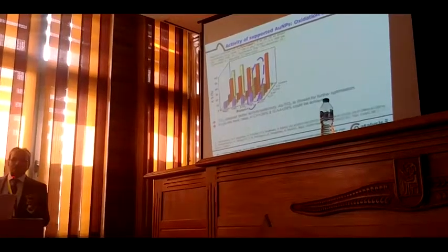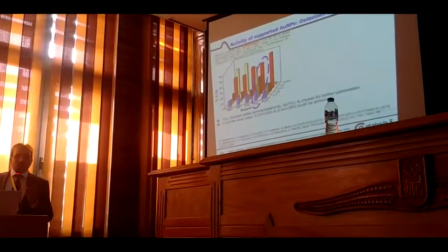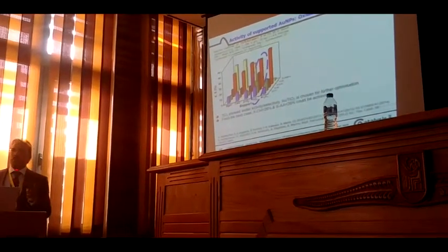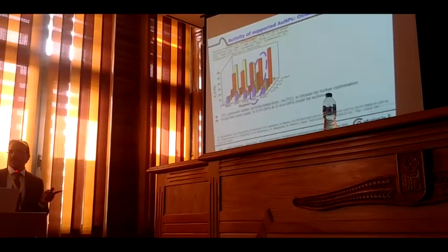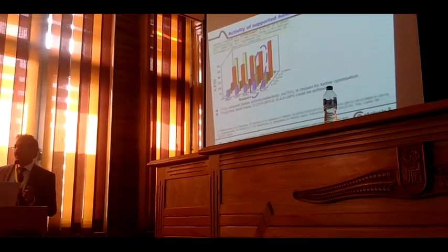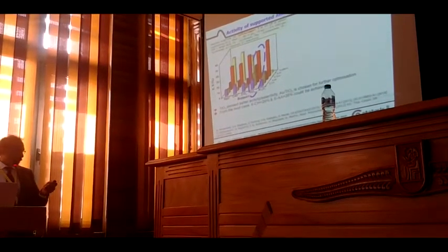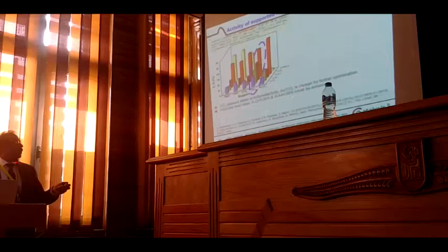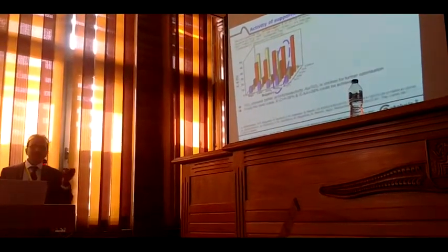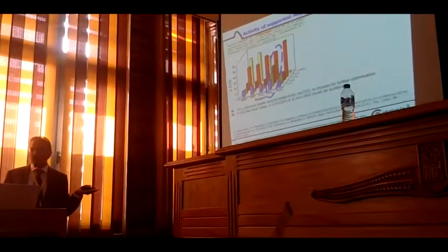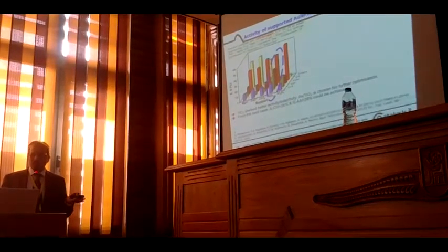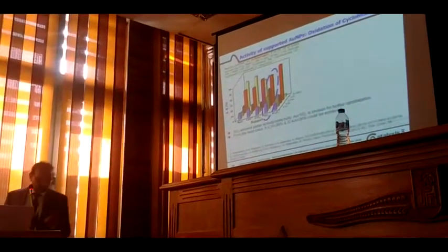But still, until now, to our knowledge, there is not even a single publication where adipic acid is produced in one step directly from cyclohexane. We are the first to claim this formation of adipic acid in one step from cyclohexane. The conversion and selectivity achieved roughly 26 and 26%, which is not really very high for commercialization, but this is the first knowledge on this approach. So we just show that it is possible. In the future, probably it might go further.